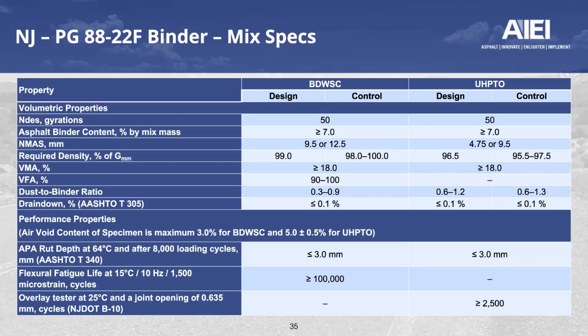In New Jersey, for their rutting performance, they look at the APA as their tool. They are testing that, as we can see, at 64 degrees C, a standard 8,000 loading. No more than 3 millimeters of rutting is allowed. They do beam fatigue testing on the bridge deck at 1,500 microstrains at 15 degrees C, and they need to exceed 100,000 cycles on it. For the thin overlays, they're relying upon the overlay tester developed in the state of Texas at 25 degrees C. And you can see that they also have a pretty high requirement there and it has to exceed 2,500 cycles.